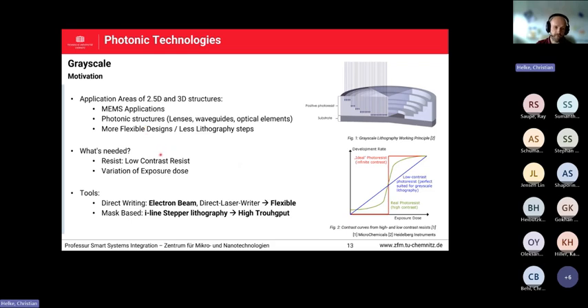And what is needed for this one? First of all, you need a resist which has the capability of dealing with 3D or grayscale lithography, and that does mean that you need a low contrast resist. If you look at this graph, for example, you see in red the ideal photoresist, and on the x-axis is the exposure dose, meaning at a certain point the light which sees the photoresist, the area of the photoresist is, let's say, exposed and will be removed in the development if you have, for example, a positive photoresist, or remains if you have a negative photoresist after development, meaning that you have a 1 to 0 binary dependency of those structures afterwards.